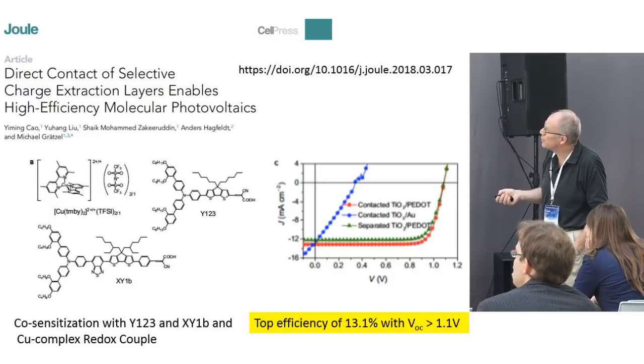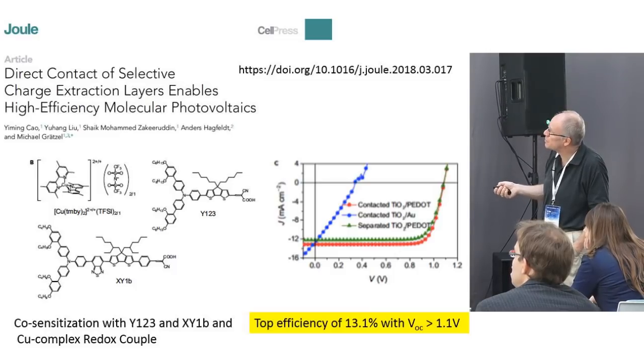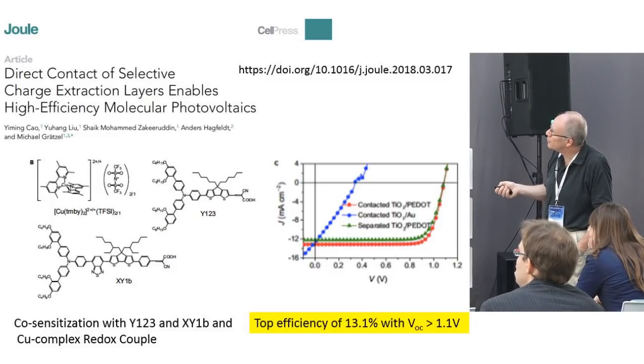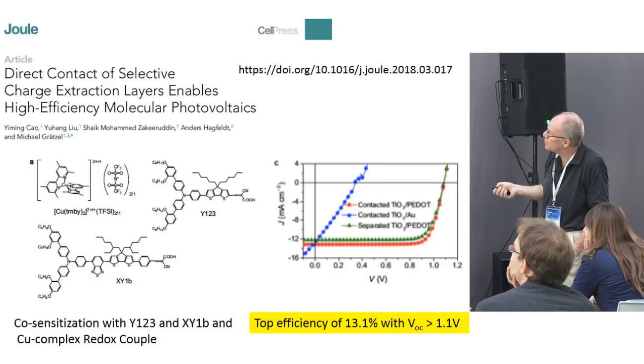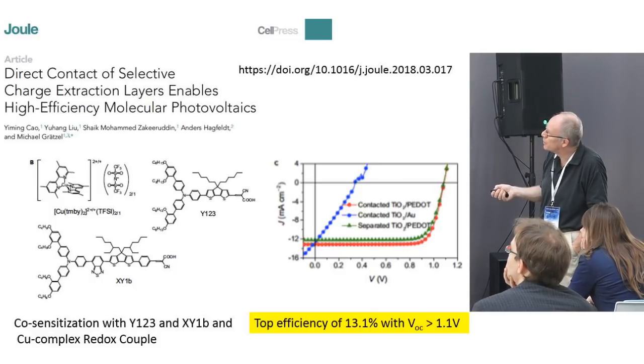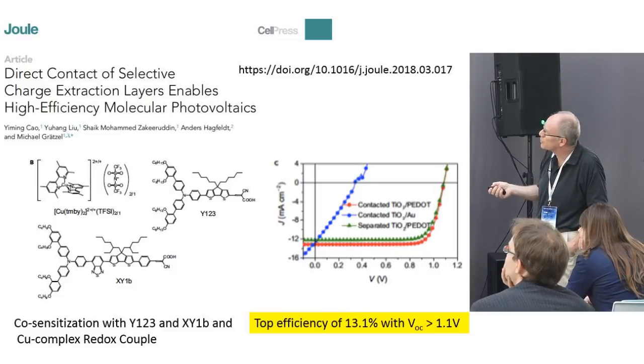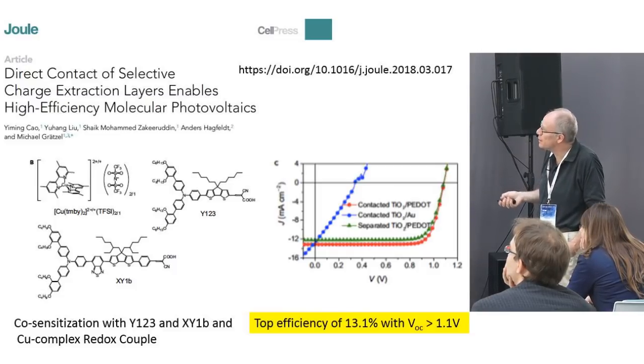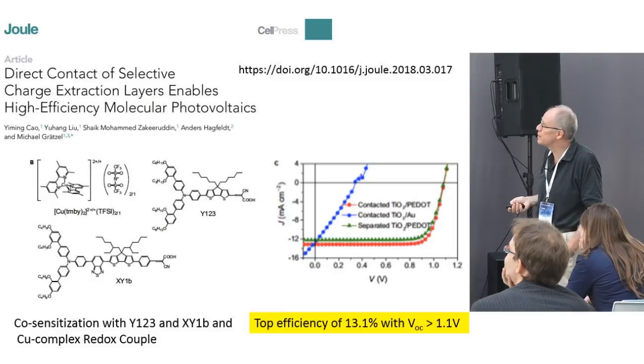And these are now the dyes we are using, so it's not based on ruthenium anymore. We have designed them to get good efficiency, of course, but also to passivate this recombination by these alkoxy groups here. So that's the state of the art at the moment, I would say.